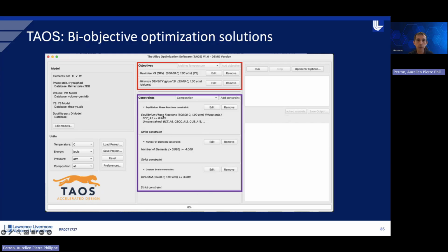So I want my alloy to be single phase BCC at 800 C. I want to have at least 4 elements in my alloy. So I really want to stay in this 4 elements design space. And here regarding ductility, this is a ductility parameter model. So that's the machine learning model. I want this value to be at least above 3 because we think it's good for manufacturing based on experience.